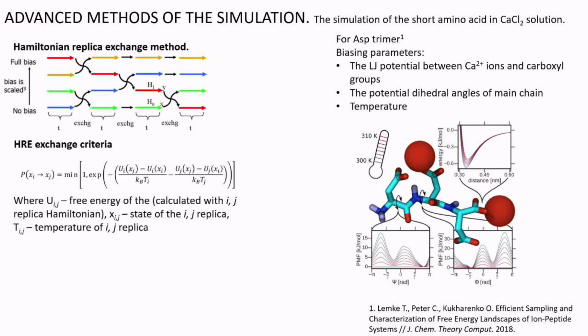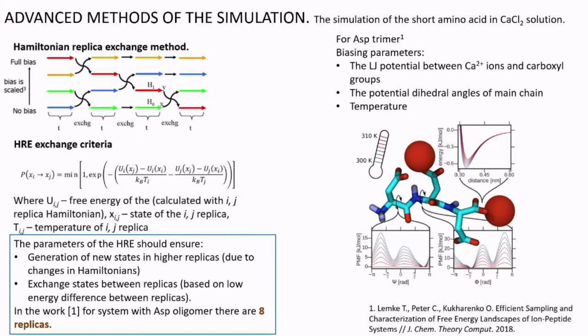And also we increase the temperature to increase diffusion of water and calcium to obtain faster new states of the system. So this Hamiltonian allows and ensures generation of new states in higher replicas. And the second thing that we have to ensure is the exchange of states between these replicas. To make it, we have to choose replicas with close energy between them, because it's one of the parameters that determines exchange between states. And in this work, there were 8 replicas, simulation of 8 replicas.